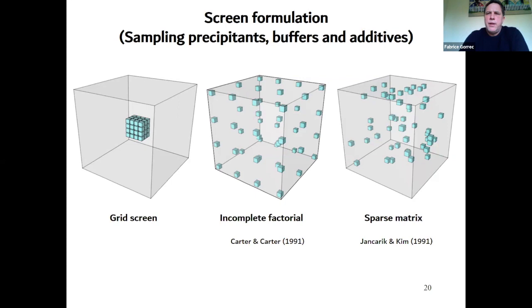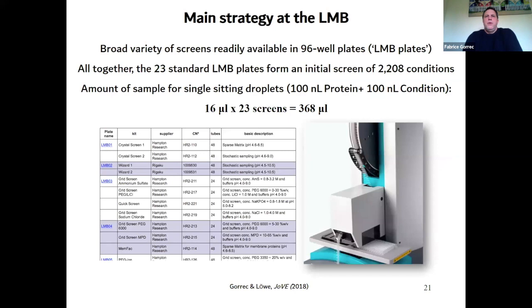There's an alternative for formulating screens, which is to base the formulation on additive mixes, but I'm not going to introduce this today. Our main strategy at the LMB, at least for novel samples, is to offer a broad variety of screens that are already available in pre-filled 96 well plates, which we call the LMB plates. That means that people can choose a screen which is assumed to be more appropriate to their sample. Although we would advise to do a large initial screen where you take the 23 LMB plates that all together form a large initial screen of 2,200 plus conditions.